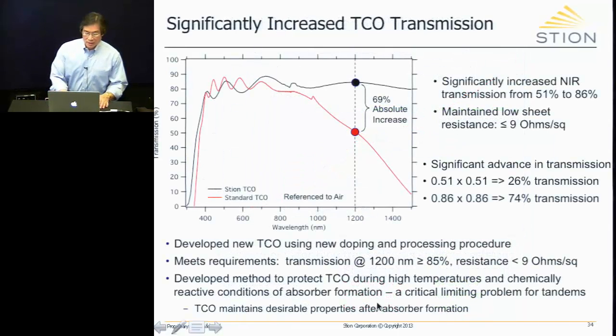So moving on, this is a transmission spectrum that partly answers your question. This is reference to air as well. So a typical TCO looks like this. All TCOs transmit very well in the visible because the free carrier absorption is in the near infrared. I believe it goes as lambda to the third power or something of that kind. It'll kill you. Right? But in the near infrared, where you need to have highest transmission to the bottom device, it drops significantly. This is a typical TCO.